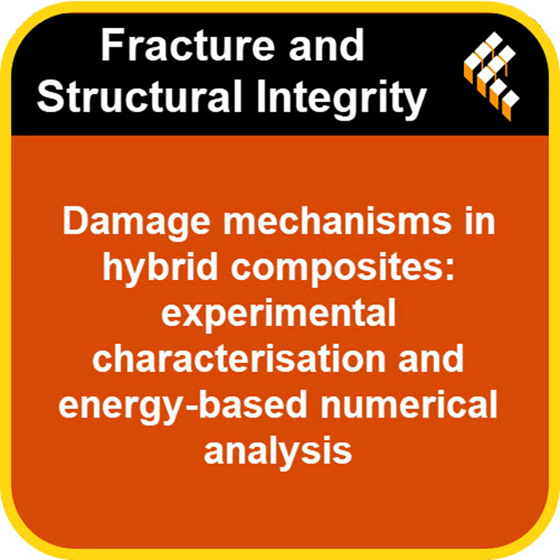Right. Carbon fibers, while they're stiffer and can handle more pulling force, tensile strength, are more brittle and not as strong when you try to compress them compared to how strong they are in tension. Okay. So when you have fiberglass on the compression side, its ability to deform more and absorb energy seems to delay when the whole thing starts to break down catastrophically. It props it up a bit longer. So carbon fibers are more likely to just snap when squeezed, while glass fibers can take more of a squishing.